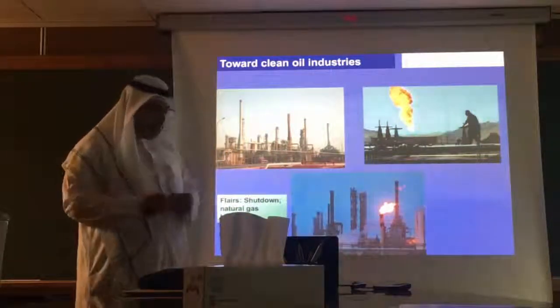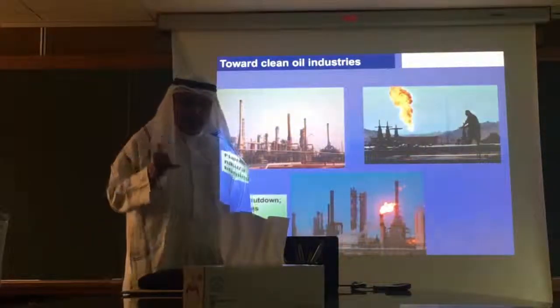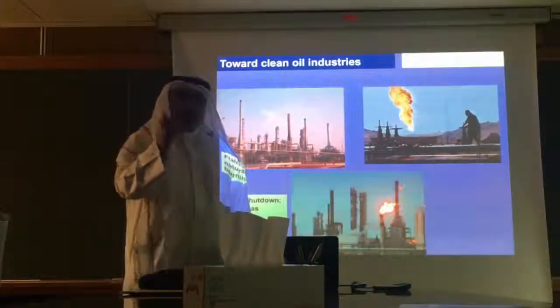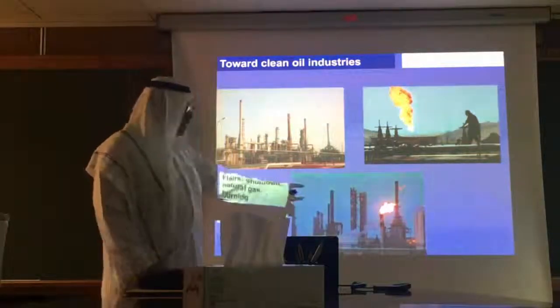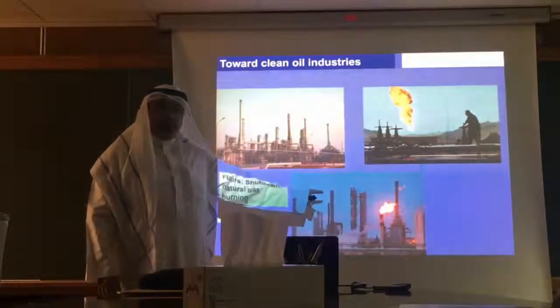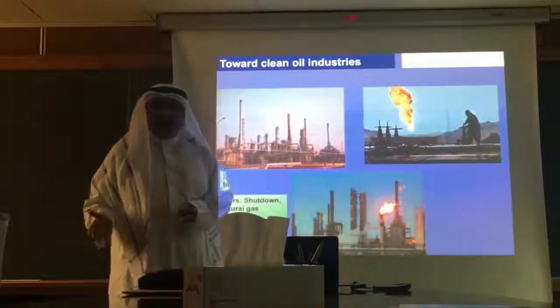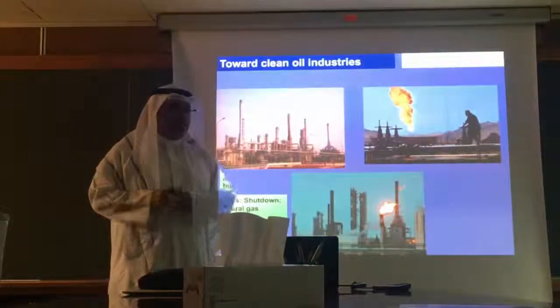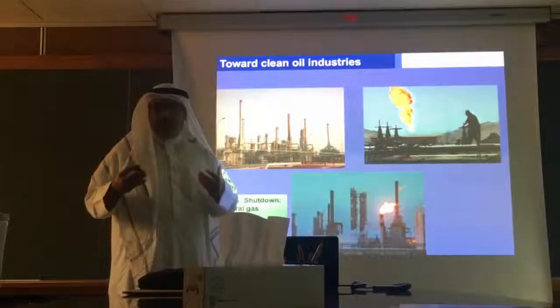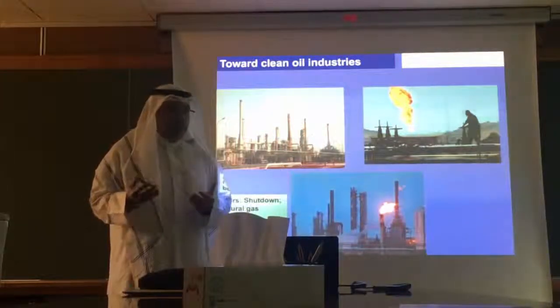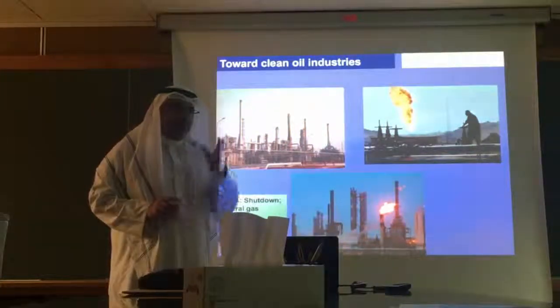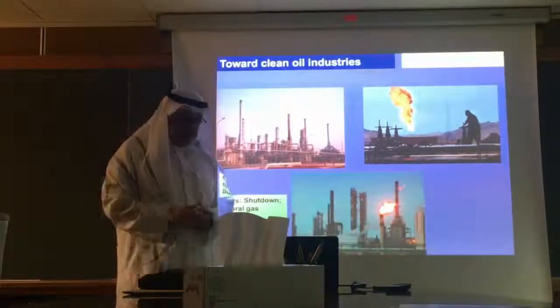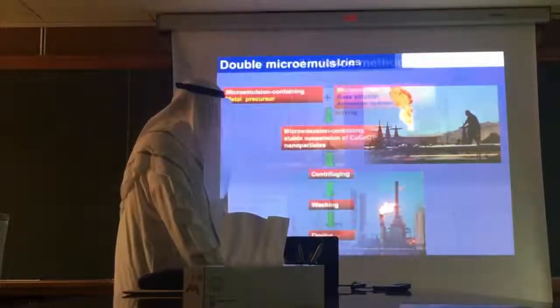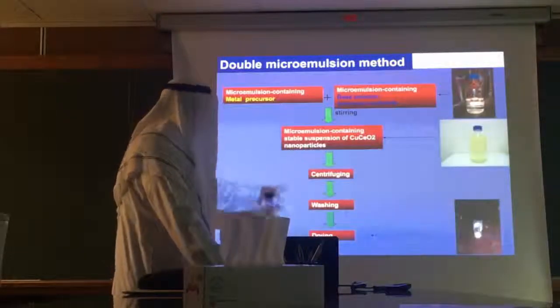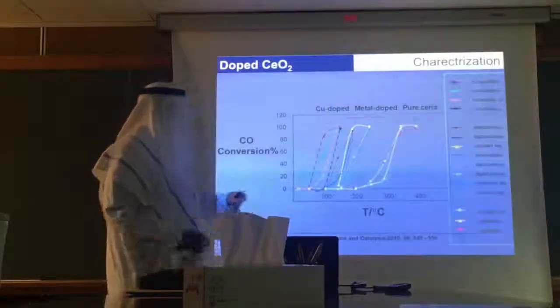So I was trying to use nanoparticles, nanocatalysts, that will drop the burning of natural gas from 1,400 to 1,200 or 1,100. This will do a huge difference. If you just drop it by 100 degrees, a huge difference will be made. You will drop the NOxes by a large amount. So I did a lot of work, and I will show you quickly. This is how I prepared the nanocatalyst.